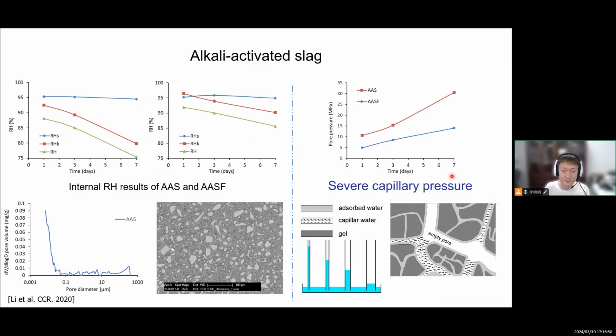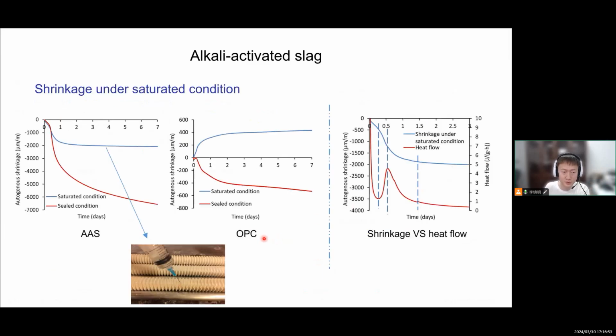But besides this, there are other mechanisms, because if we put the Portland cement in the saturated condition, there will be expansion because of the formation of ettringite, which means that the only reason for the shrinkage of Portland cement is capillary pressure. But if we put AAS in saturated condition here, there will still be a large part of shrinkage, especially in the early age, which means that self-desiccation is not the only mechanism here.